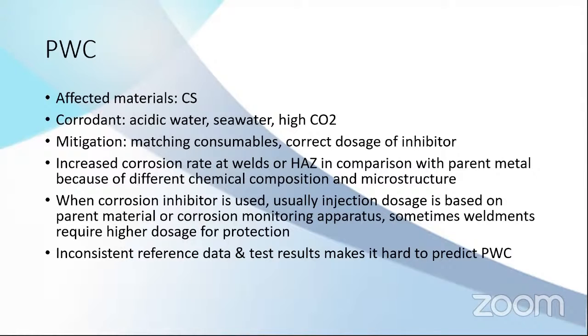And this is the problem when we are forced to use consumables that are not matching. For example, if we are adding nickel to increase the low temperature resistance, to increase the impact strength, it can increase or it can decrease the corrosion resistance. So it's hard to predict if PWC will happen or not. So the best option is to always use matching consumables to mitigate this problem, so you don't have any chance of PWC.